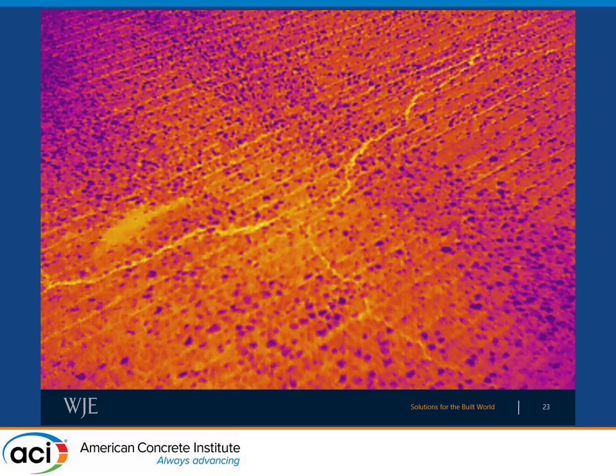Normally you have to do it where there's some sort of temperature contrast, either in the morning where the concrete might be cool and the top surface is just starting to warm up, or later in the afternoon where the concrete's warm and the surface is starting to cool. But because it was warm earlier in the day and then the surface started to cool, these cracks really started to stand out quite a bit.